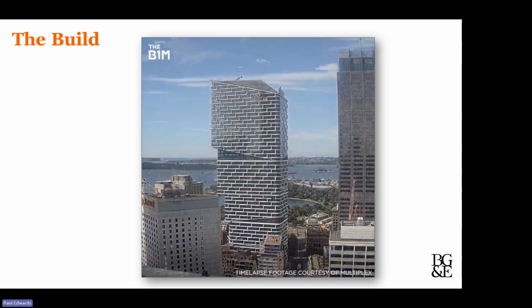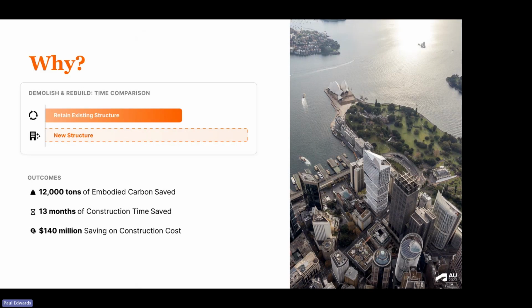And if you take your mind back to where the initial investigation revealed that maybe 10 to 15 floors might have needed that level of intervention, I brought that down to only 2. It's quite a significant saving. There were 28 walls that needed tension strengthening down towards the bottom of the south face of the core. This due to just the change in loads due to the new profile of the building. So you, again, take your mind back to the 4D model where the loading, I'll just go back a couple of slides so you can see it.